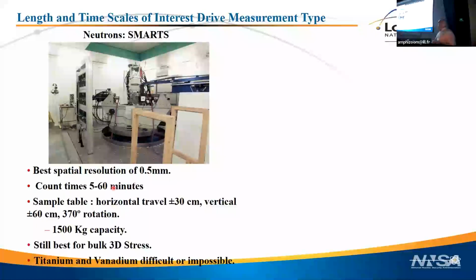Count times can be 5 minutes to 60 minutes. We can move big parts around, so we've done 1,000 kilogram parts, 1,500 kilograms is our capacity. I still would argue that for bulk 3D measurements in large parts, neutrons are still the way to go because of some of the details of X-rays. But titanium and vanadium are very difficult or nearly impossible because of the coherent cross-section of the two. Don't need to go into details.